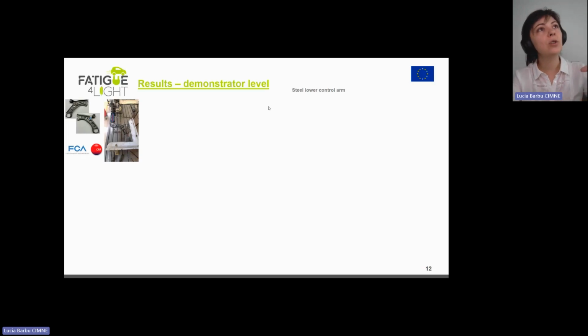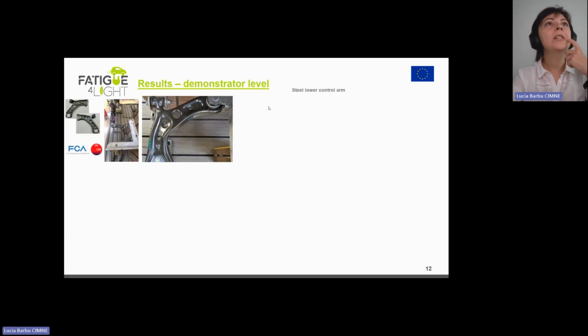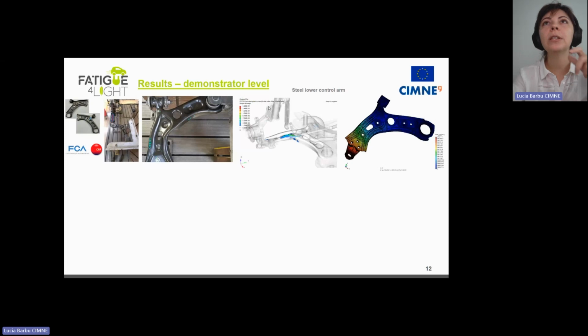And here you can see this demonstrator was manufactured and tested by CRF. You can see some images of the tested demonstrator, and here you can see the test setup for studying the experimental behavior, first in the monotonic range and after that in the cyclic range. Here you can see an image of the failed component under the monotonic regime, or the monotonic test,